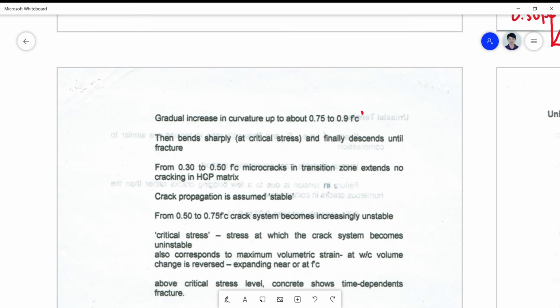From 30 to 50 percent of f'c, microcracks in the transition zone extend, with no cracking in the HCP matrix yet, so this is still stable. You call it stable condition. But from 0.5 to 0.75, the crack system becomes increasingly unstable. Here we can now define what you call the critical stress: the stress at which the crack system becomes unstable. It also corresponds to the maximum volumetric strain, at which the volume change reverses direction, expanding, near or at f'c.